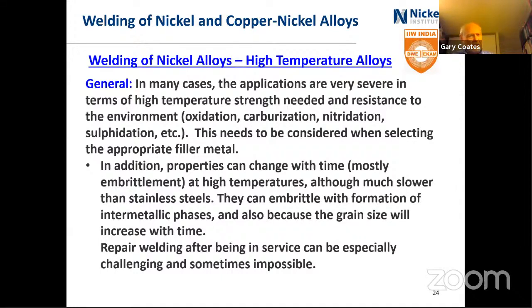And one of the things that is different with high temperature alloys, whether it's stainless or nickel alloys, is that the properties, the metallurgical structure of the material can change with time. And most often that means they embrittle with time. Now they take a much longer time to embrittle, but if you have a material that's been in service for 5 years, it might be quite brittle. They embrittle because of intermetallic phases, but also the grain size will grow. And when you have large grain sizes, all the impurities in the material go to the grain boundaries, and it makes it very easy for the grain boundaries under high stresses to separate. And so sometimes repair welding is very challenging, and sometimes it is impossible. Such a webinar on doing the high temperature alloys is really the subject of a separate webinar.